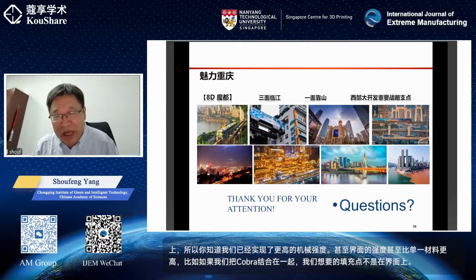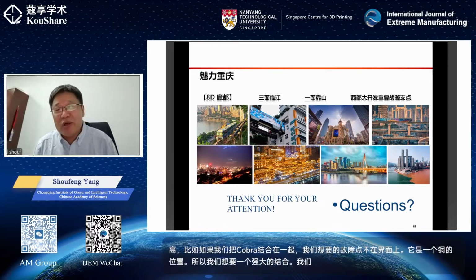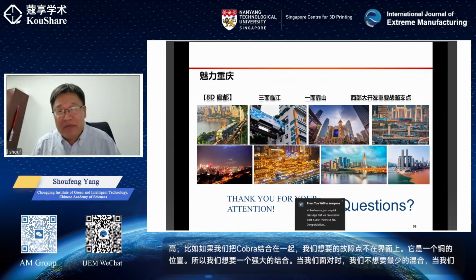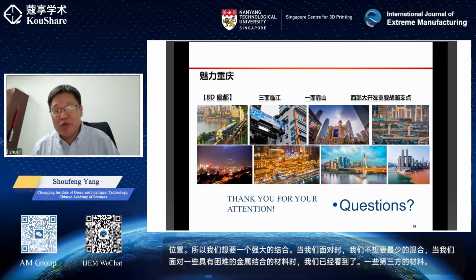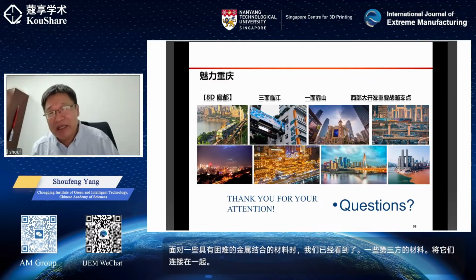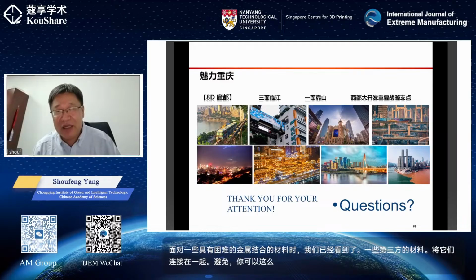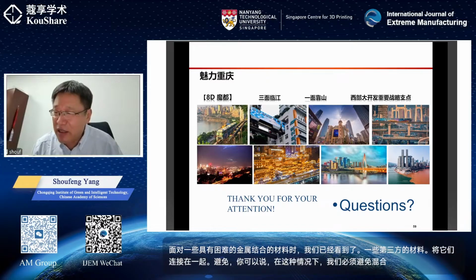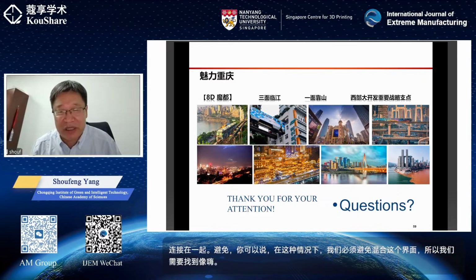So we want a strong bonding. We don't want minimum mixing, but sure, when we face some materials with difficult metallic bonding, we have to think about some third material to bridge them together. In this case, we have to avoid the mixing at this interface. So we need to find something like high entropy materials. We have found something that's like each other.